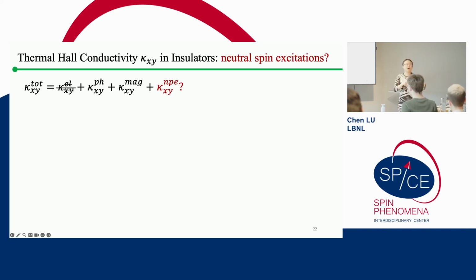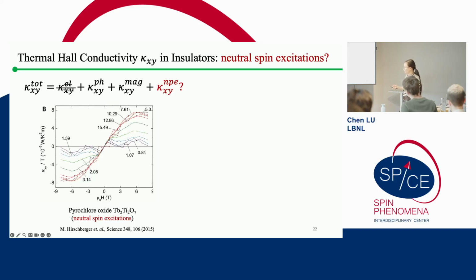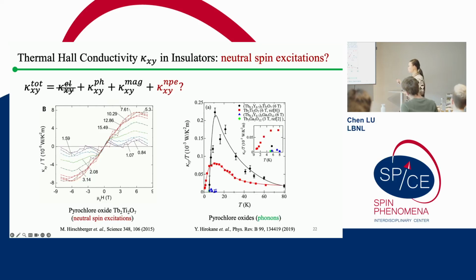Okay, so before I talk about phonons, let's talk about the other things. What are other types of neutral excitations that can probably also give you a thermal Hall effect? Back in 2015, Professor Ong's group reported a non-zero thermal Hall effect in a pyrochlore material. Back then, they believed this non-zero thermal Hall effect came from some neutral spin excitations, maybe spinons in these materials. But later on, another group in Japan tried to repeat this type of measurement in a substituted system, and their conclusion was slightly different. They were more inclined to believe the signal was generated by phonons instead of magnons.